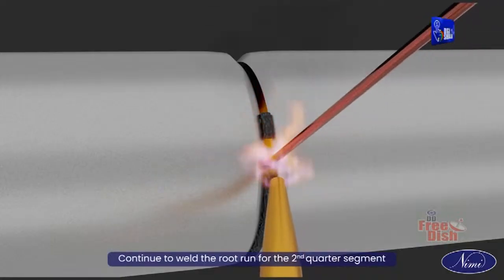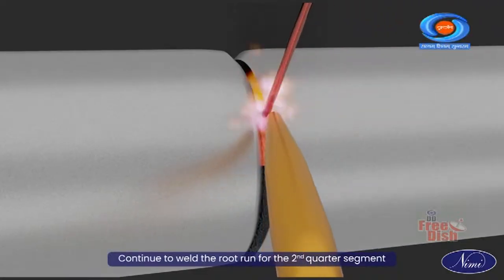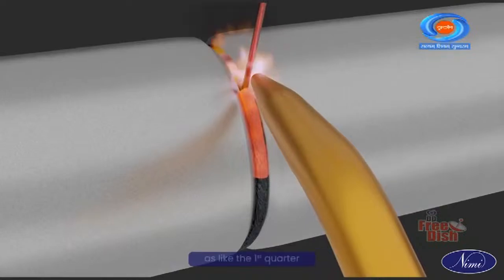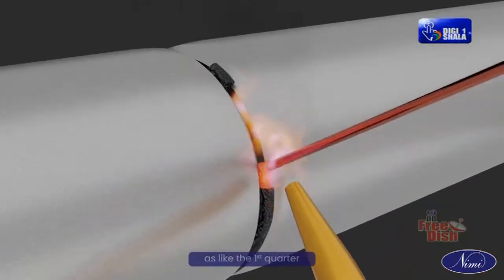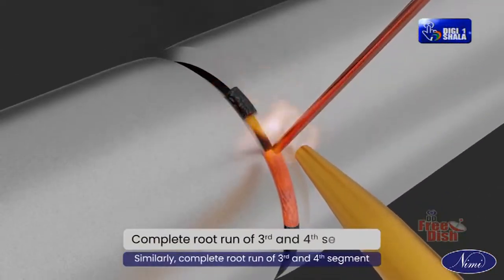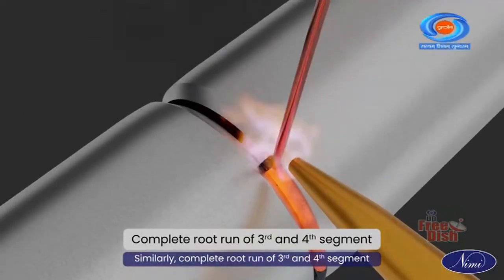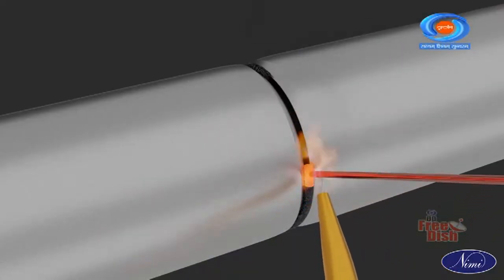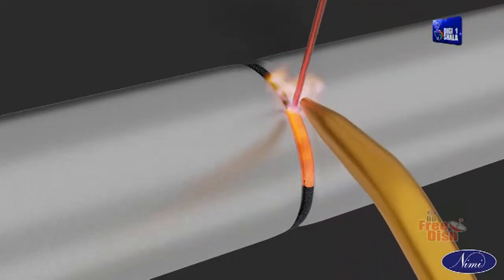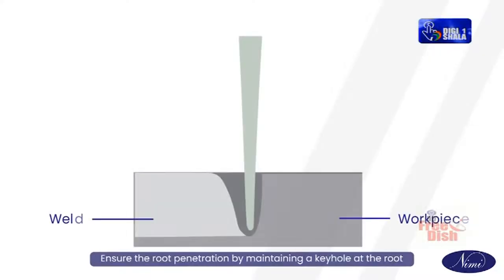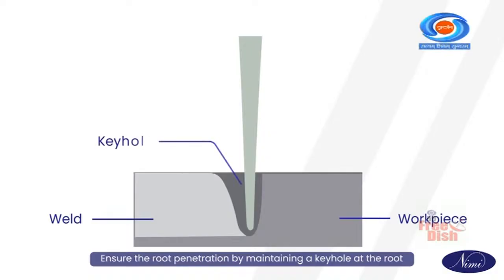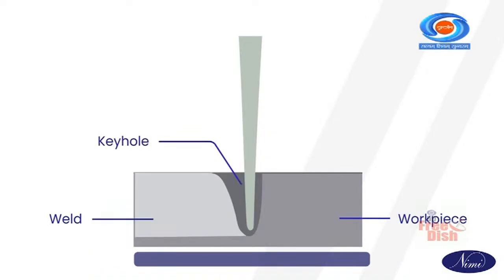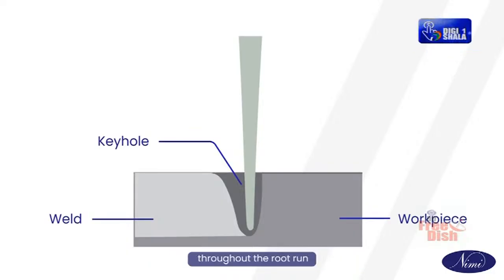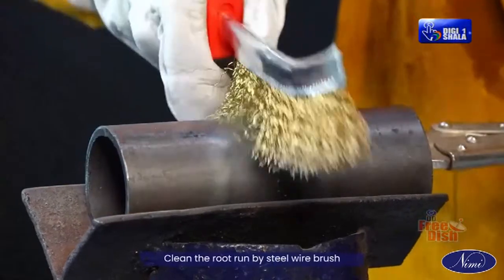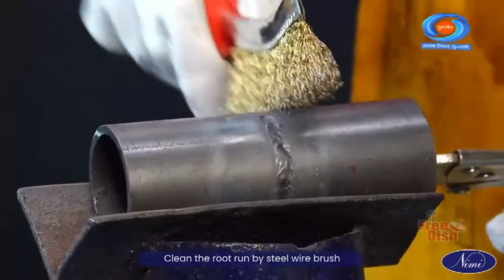Continue to weld the root run for the second quarter segment as like the first quarter. Similarly, complete root run of third and fourth segment. Ensure the root penetration by maintaining a keyhole at the root throughout the root run. Clean the root run by steel wire brush.